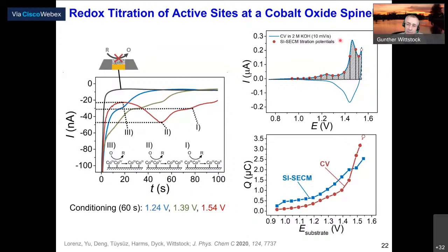So here you see a cyclic voltammogram of such a spinel oxide electrode. You see different redox signals, and now we made such surface interrogation mode at the indicated potentials. I picked 3 of the curves here at these potentials. So 1.24 volts, that would be about here, on the peak, then 1.39, that would be here, and 1.54, that is after this peak. So if we apply a potential of 1.24 volts, this species is generated, and then if we make a titration, we see a decay, a plateau, and then the final decay.